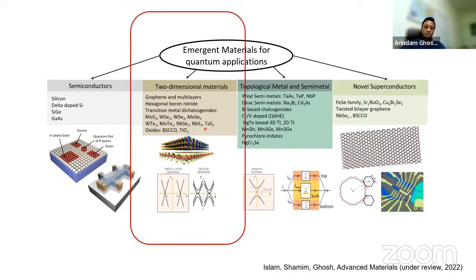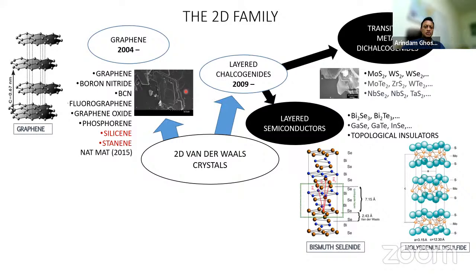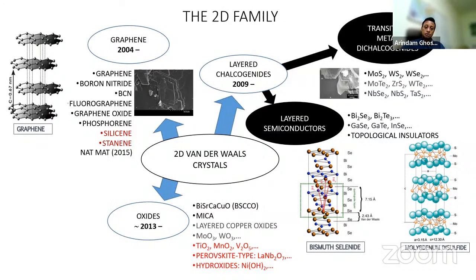For example, there are about 30, 35 two-dimensional materials, a little more maybe now, which people have measured. Graphene is one of them. The chalcogenides, transition metal dichalcogenides, the layered semiconductors like the topological insulators. These are all two-dimensional materials because their out-of-plane layer-to-layer interaction is much weaker than the in-plane interaction, and that is why you can exfoliate them mechanically and form individual layers. And you can have oxides as well. The high temperature superconductors, some of them are also two-dimensional materials or layered materials per se.